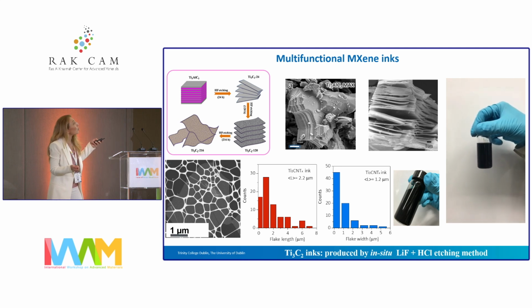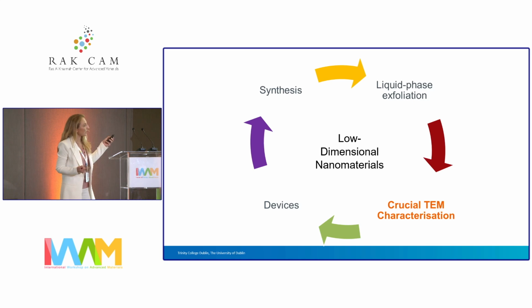This is because once you do the etching, you end up with a lot of oxide groups, OH groups, fluoride groups, and these are actually the ones that make most of this material, MXenes, and in this case, titanium carbide, Ti3C2, an extremely good electrical conductor, mechanically very strong. So I'll show you some of the applications we are chasing.